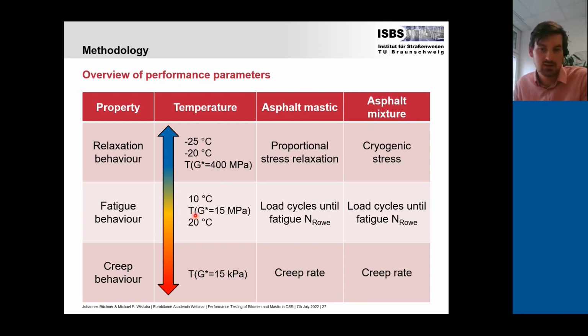In the intermediate temperature range, this 15 megapascal is also in the range of 15 degrees, and in the high temperature range, this is the value which we already introduced into the European standard as a shear modulus temperature. So we test each material at a specific temperature where the binder has the same stiffness, the same shear modulus.